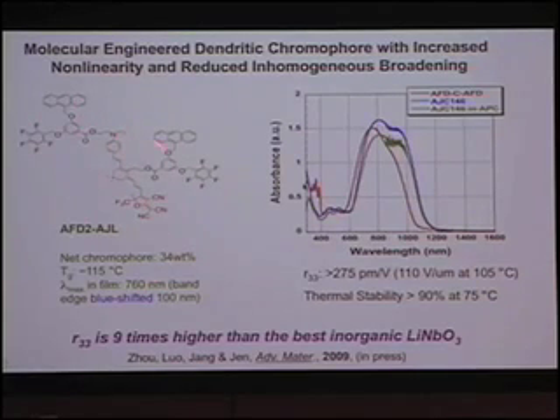When you tailor the environment around, for example, this molecular dendrons molecule, you can see they have a much narrower absorption, because if you take this chromophore and dope it into the polymer, you can form aggregates and form inhomogeneous broadening of your absorption. Then this can actually have a much narrower absorption. And just this one molecule by itself is already almost 9 times that of lithium niobate.